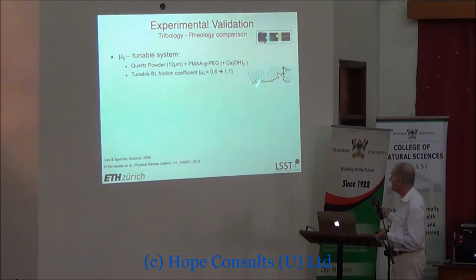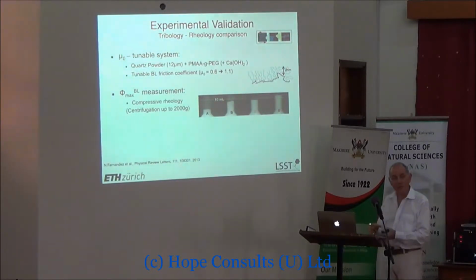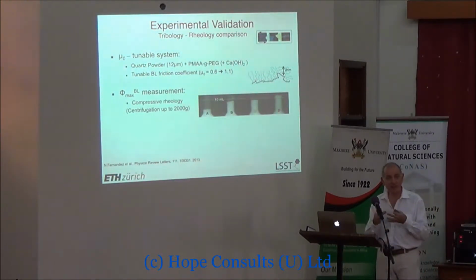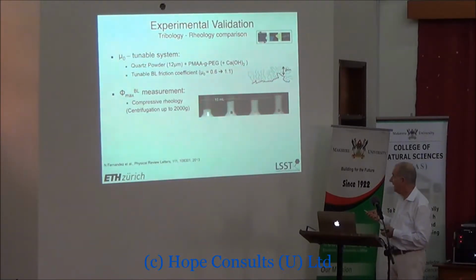Now, in the lab we were able to tune the surface friction of these cement grains by putting in the kind of polymer brushes I was talking about before. They just spontaneously stick to the surface of the cement grains. We were able to vary our boundary lubrication friction coefficient between these values. And we could see how well the grains were sliding over each other by making a slurry of grains and then centrifuging it. The better they slid over each other, the more the grains would pack. And we could use this as a very quick and reliable way of seeing how efficiently the cement slurry was able to flow over itself.